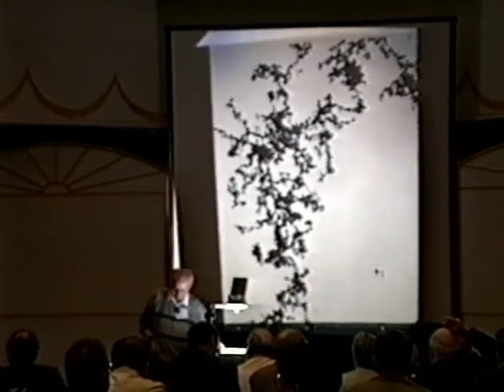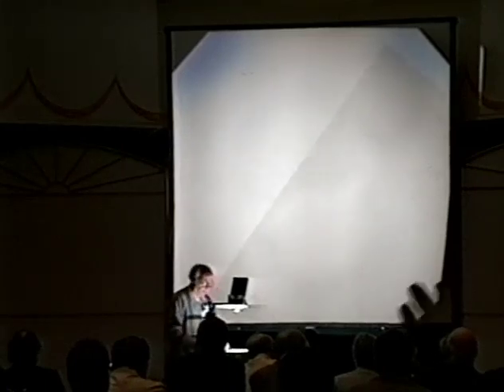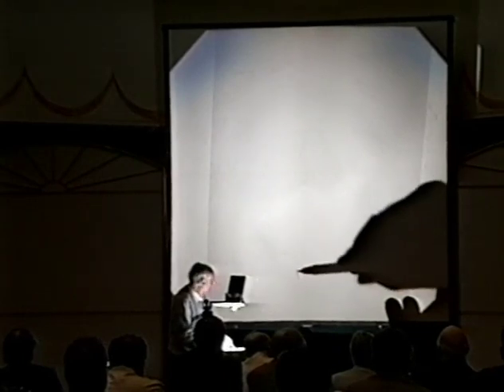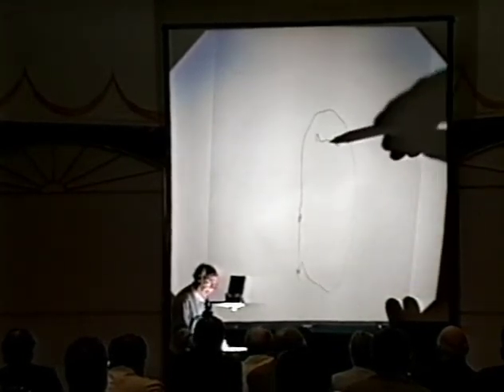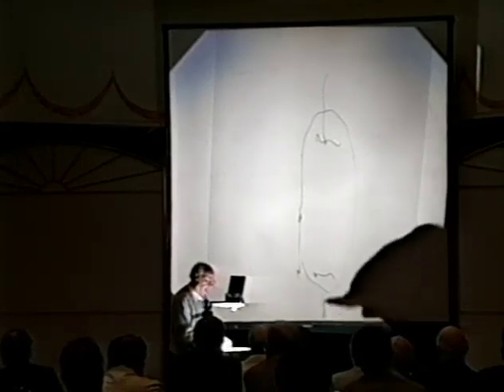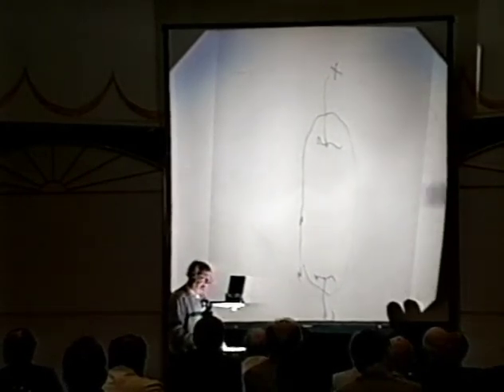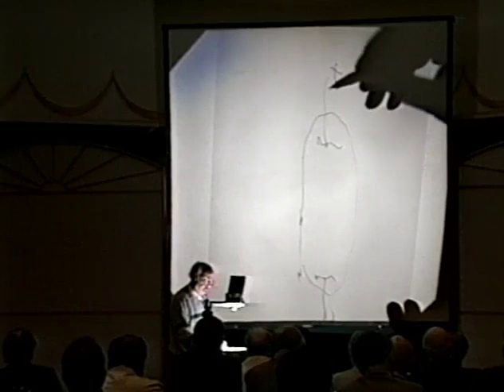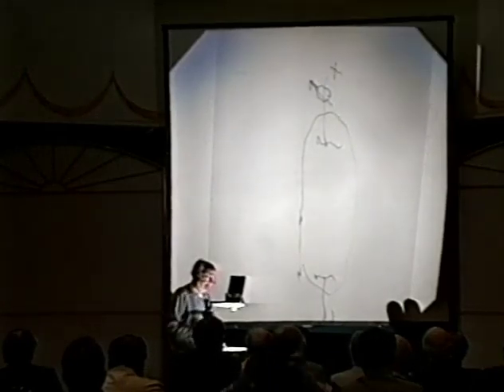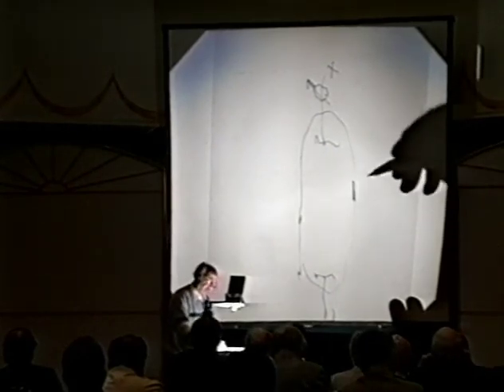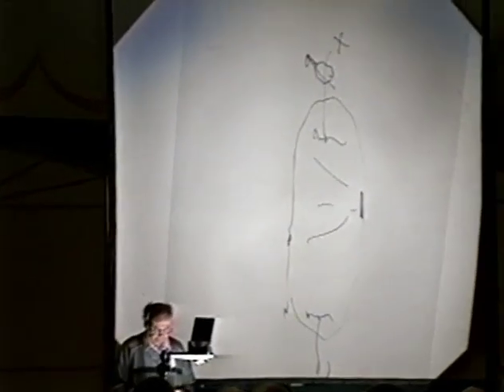At this time, there was a technological problem with gas discharge tubes. If one applies the voltage on the tube, there is a time lag between the application of the voltage and the ignition of the discharge. To reduce this time lag, a small amount of radioactive material is applied in the tube at a suitable place. Our titanium preparation, where we have absorbed some tritium, was very suitable for this purpose.